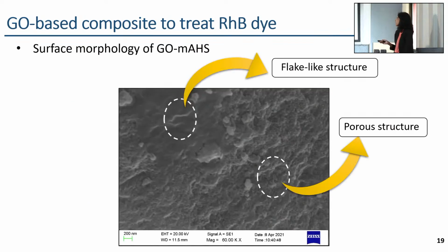Here I have shown the SEM image of the GO-based composite. We can see the porous structure of this composite, which is due to the porosity of the modified aluminum hydroxide sludge. And here we can see the flake-like structure, which is due to the incorporation of graphene oxide.